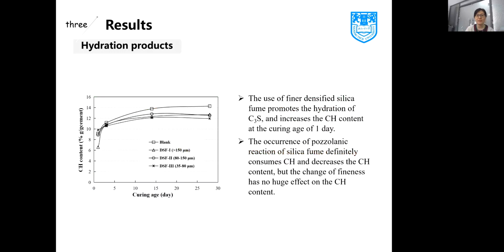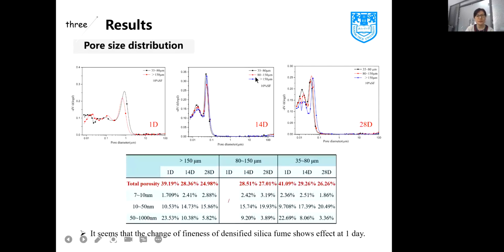The use of finer densified silica fume promotes the hydration of alite and increases the CH content at the curing age of 1 day. The occurrence of pozzolanic reaction of silica fume definitely consumes calcium hydroxide and decreases the calcium hydroxide content, but the change of fineness has no huge effect on the CH content. We also studied the pore size distribution by using MIP technique. It seems that the change of fineness of densified silica fume shows effect only at 1 day. The total porosity or the volume of different pore size has no significant change.